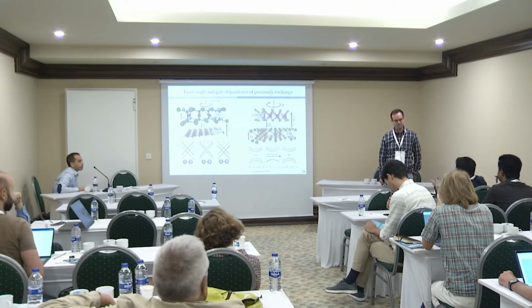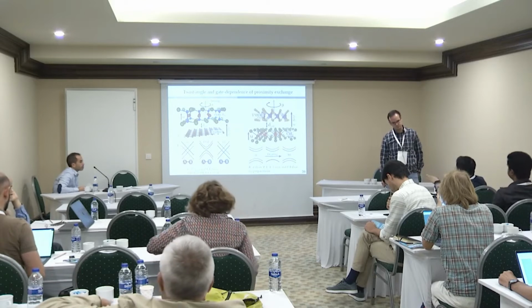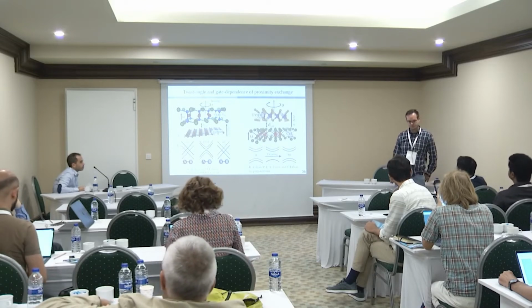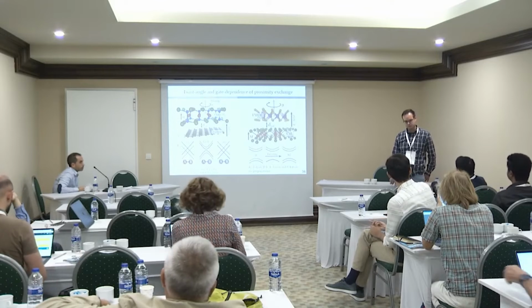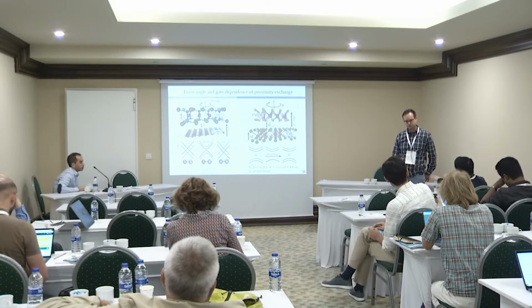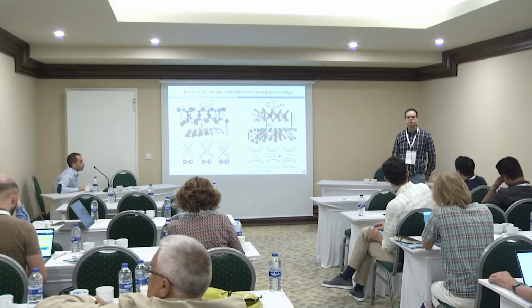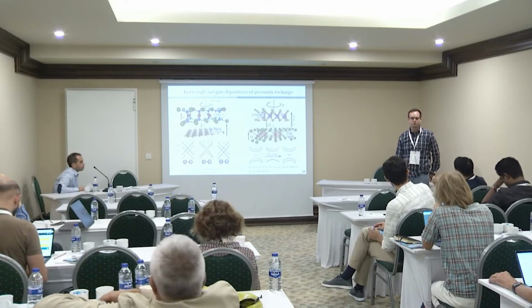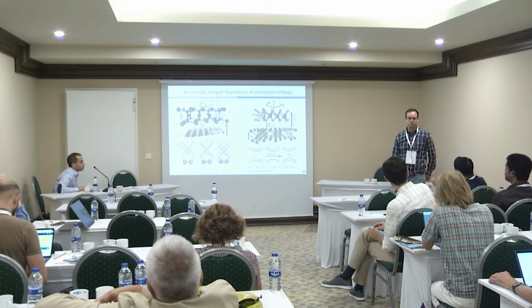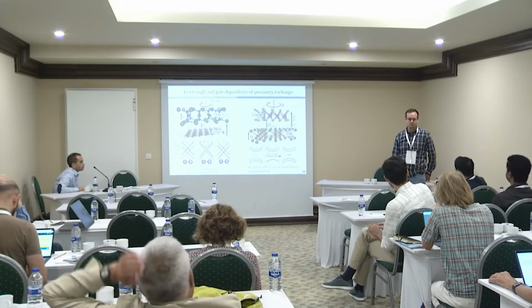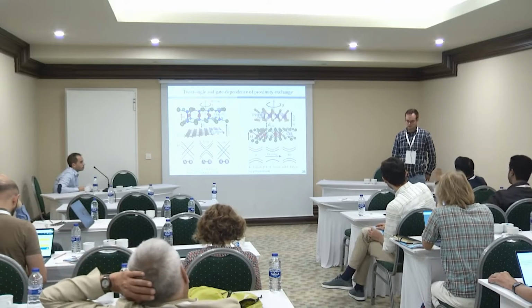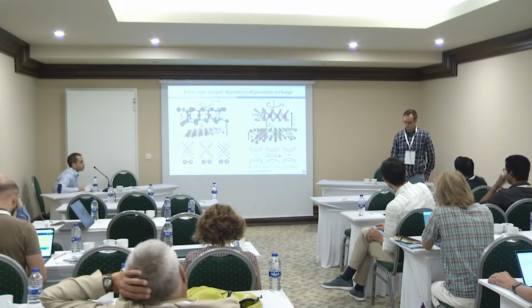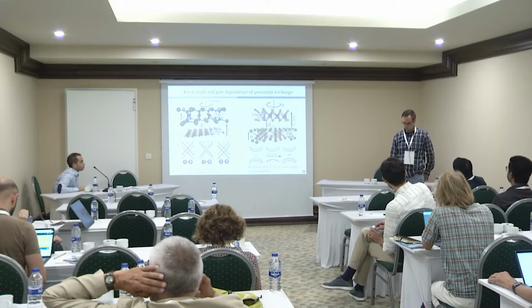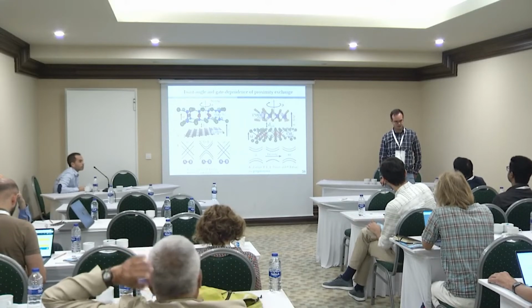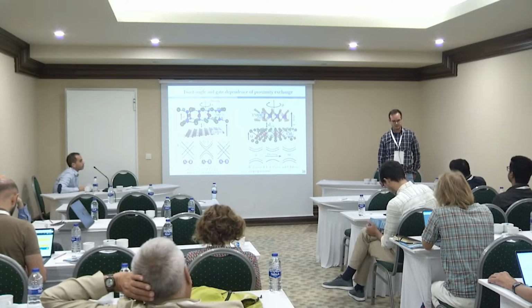Yeah. So regarding these TMDs, I know some work shows that on top of forming an interface with other magnetic materials, you can dope magnetic elements, and that could also enhance valley spin splitting. So do you think it would be interesting to approach using two different ways? One is you dope to enhance that, and then you can form the interface to further enhance the valley splitting. Sure. Yes, I think so. Absolutely. Thank you.